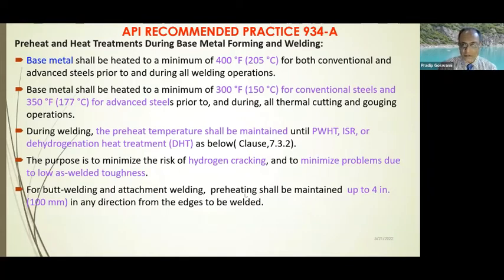And typically, the preheating band has to be maintained up to a 4-inch wide band in any direction of the welding. That means when you weld a seam, 4 inches from each side of the weld, as a minimum, this particular temperature needs to be maintained in that zone.